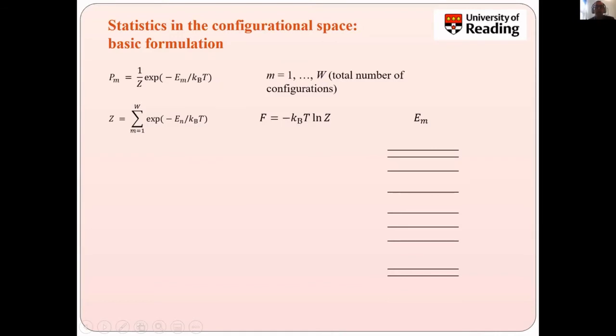But as many of you know, the partition function is also a very important quantity in thermodynamics, and it gives you access to the free energy, in this case, the configurational free energy of the system. And this configurational free energy allows you to then calculate many other things. So if you have the energy of the whole solid solution, which is taken as the average of the energies of the configurations, in the same way as for any other observable, you can calculate the average over the whole of the configurations. W here is the total number of configurations.